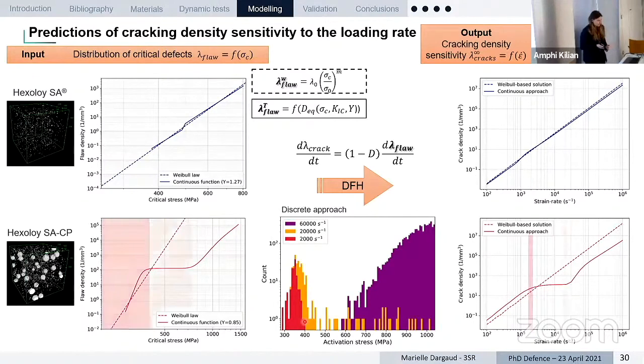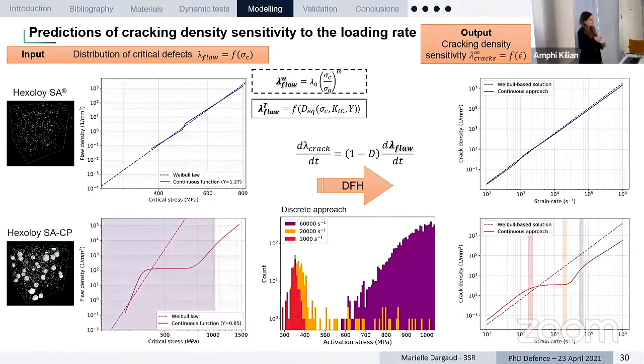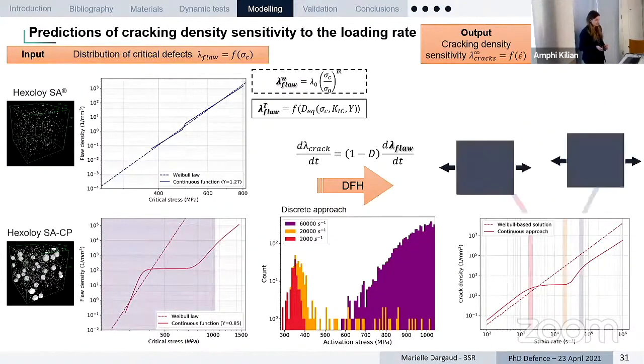When we increase the strain rate, we reach this plateau in the input function. So this is why we are actually also reaching a plateau for the cracking density. So here we limit the increase of the cracking density thanks to this plateau. And well, at higher strain rates, we start to capture the very small sintering defects. So this is why the cracking density is increasing again. So here you have a few images of a discrete simulation where you have the obscuration zones growing from the triggered cracks. At low strain rate, it's just a few defects, and at high strain rate, you have a high amount.